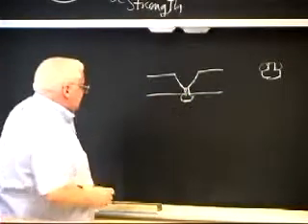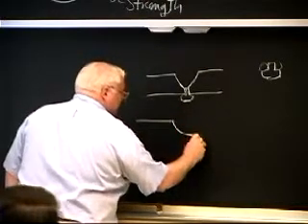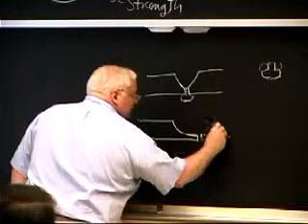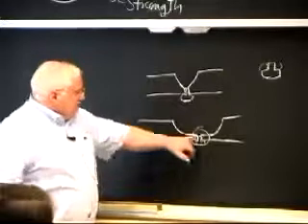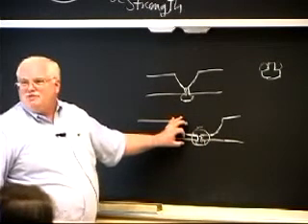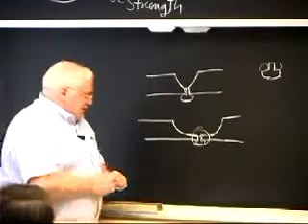And I said, well, change that joint design. Make a J groove with a long land like this. And put your EB insert in here. And make your root pass right there, so this thing is not as stiff, okay? Get some flexibility. Get rid of some of the stress on that root pass. And I said, try that.